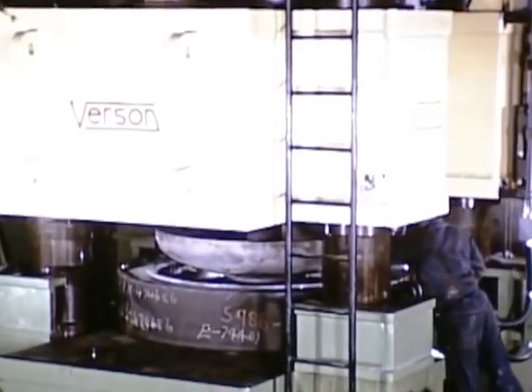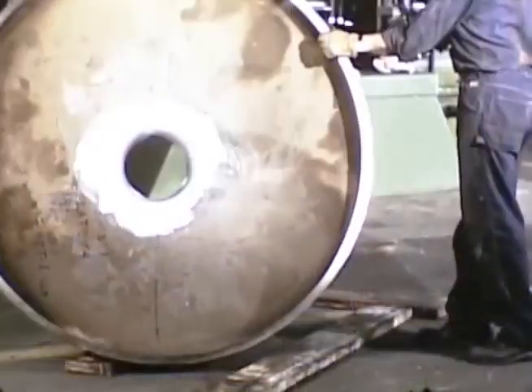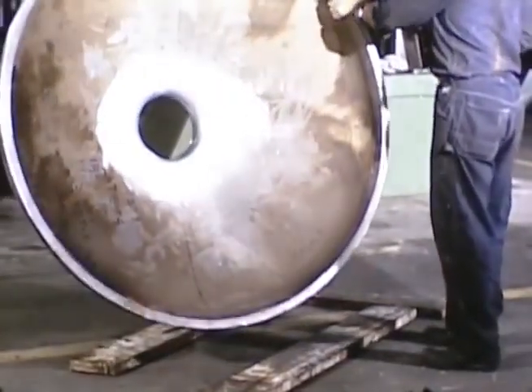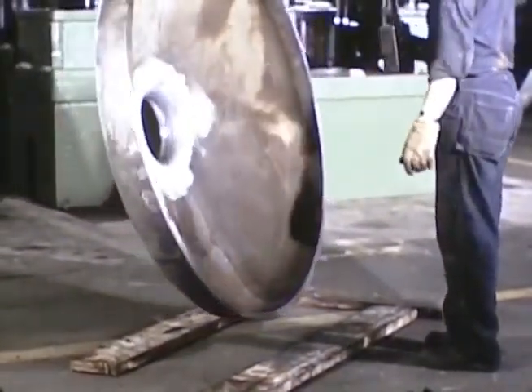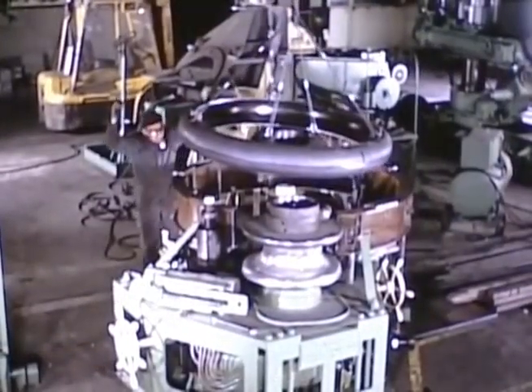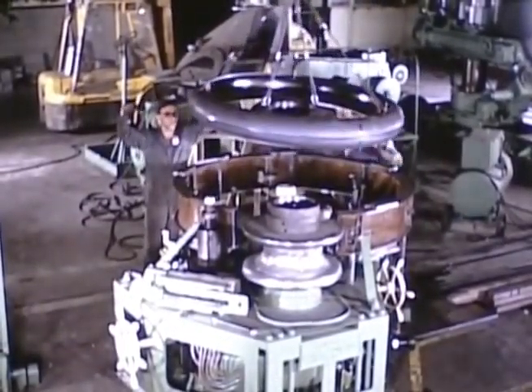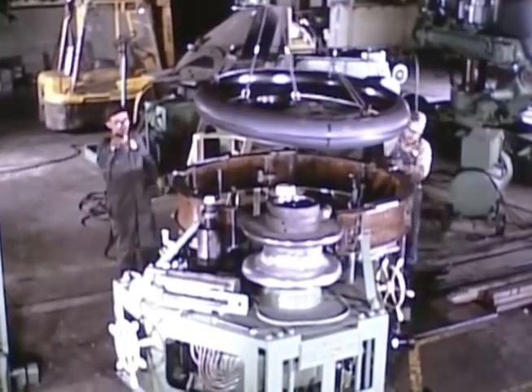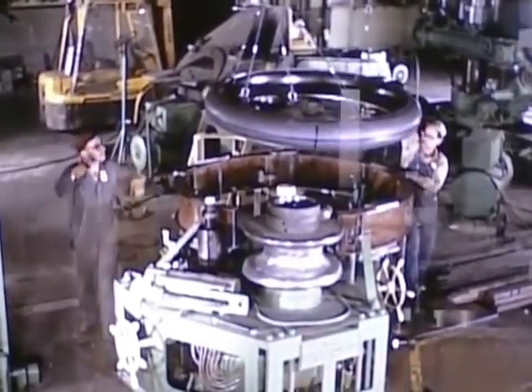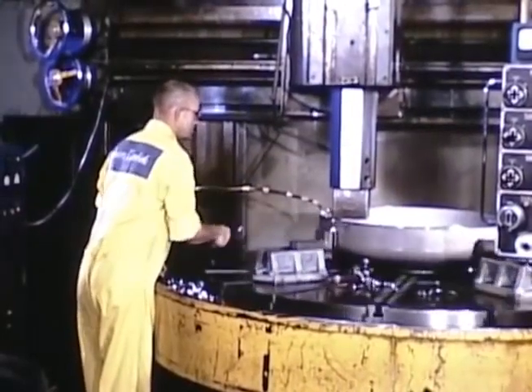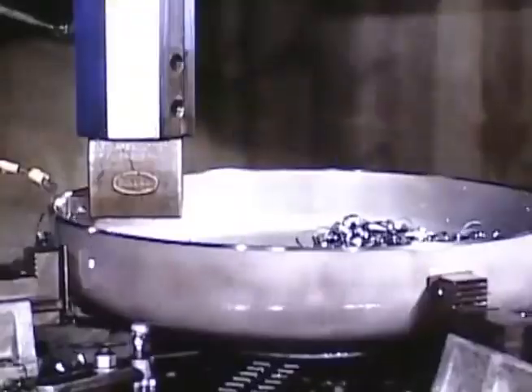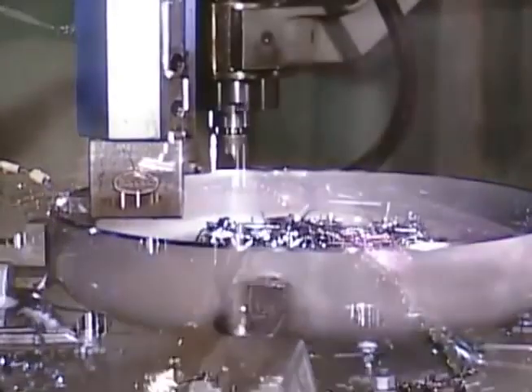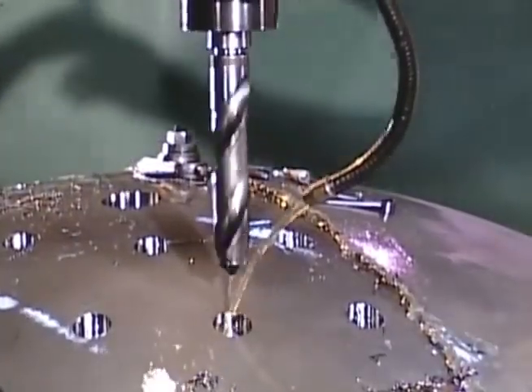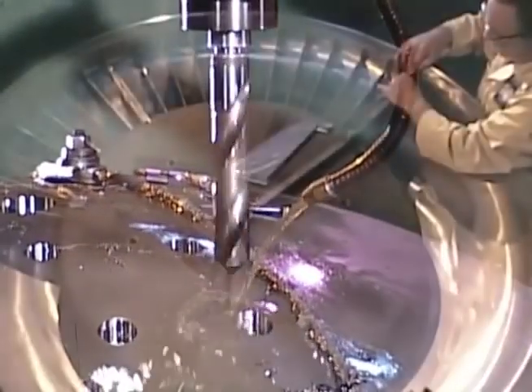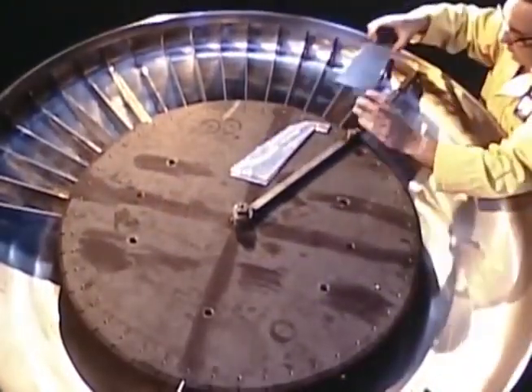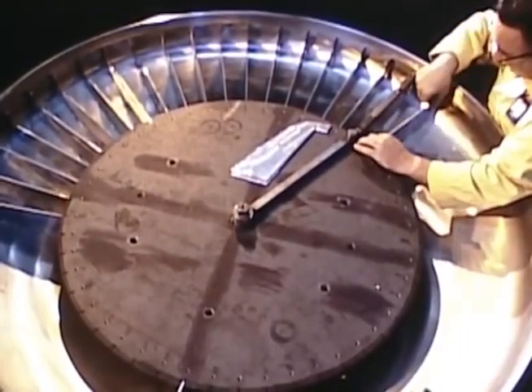Dished heads for the reactor vessel were cold-pressed from 1 1/8-inch thick Hastelloy N alloy plates. The reactor vessel's fuel inlet flow distribution channel was also cold-formed, as were most of the Hastelloy N alloy parts. Some development work was needed to fabricate major components. It was found generally that Hastelloy N presented no more problems than other high nickel alloys or stainless steel. Assembly of the reactor vessel began in mid-1962.